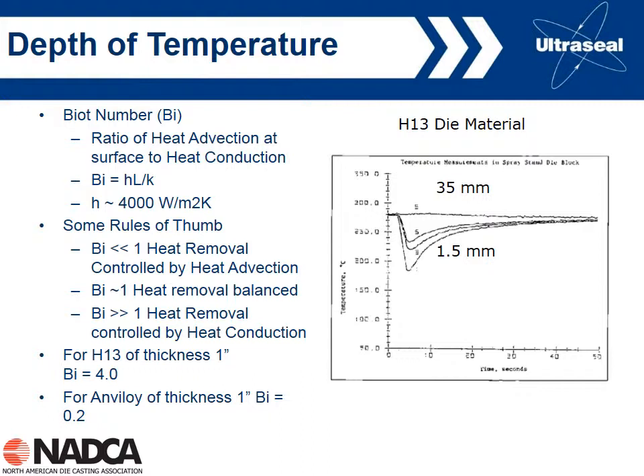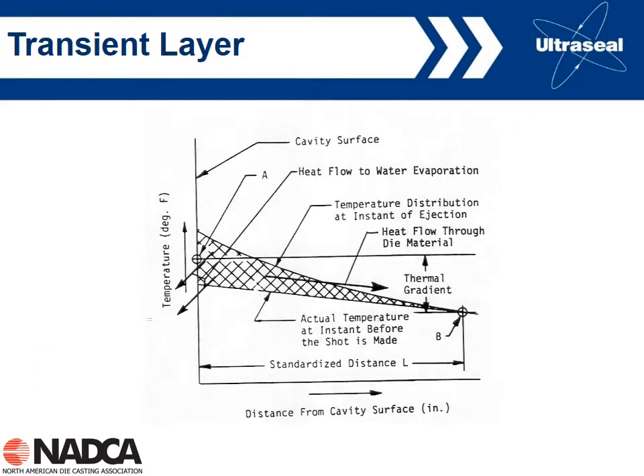We have a layer where we can affect the surface, but only an inch and a half into the die, we have very limited effect in terms of changing it, either by die spray or by the cooling lines, within the 60 seconds or so of a die casting cycle. So we have this transient layer. It's a big deal for us die casters because it limits our ability to control the die temperature and therefore to control porosity. We can affect the surface, but we have very limited effect below the transient layer of about 1.5 inches or so. And this is one of the reasons why spray doesn't really work the more we apply.